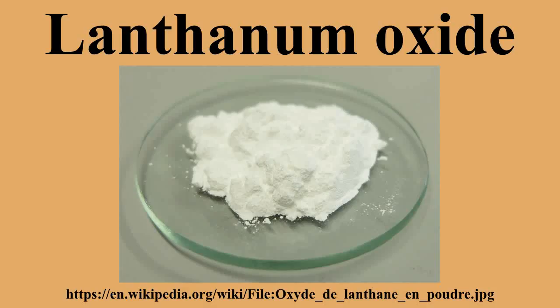La2O3 to the glass melt leads to a higher glass transition temperature, from 658 degrees Celsius to 679 degrees Celsius. The addition also leads to a higher density, microhardness, and refractive index of the glass.